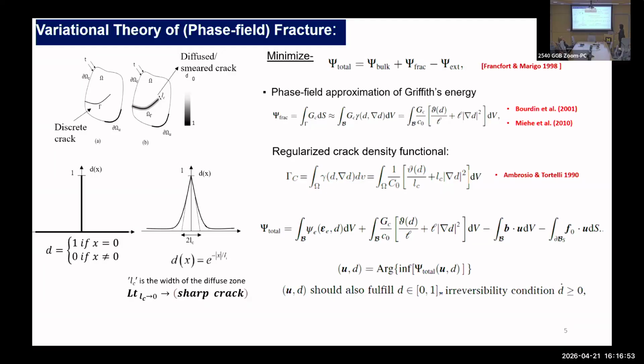Okay, so once we have that, then in the total energy term, everything is over the volumetric domain now. So we can minimize this energy by a simple variational principle to solve for not only the displacement field, but also for the damage field. So the damage field, the propagating crack path, essentially emerges as the solution of this minimization problem. Okay, and of course, along with that, this implementation further demands criteria like the damage is irreversible. So no healing is possible once the crack is happening, because we are not solving any dissipation inequality here. It's just energy minimization. So there is a possibility that if we are doing an unloading, the crack can go and heal. So we have to impose this constraint from outside, as an additional principle.